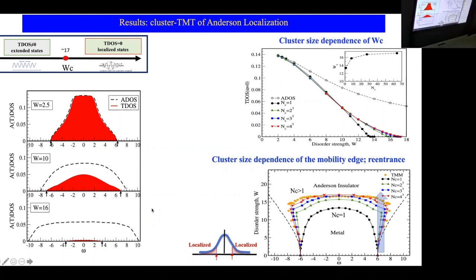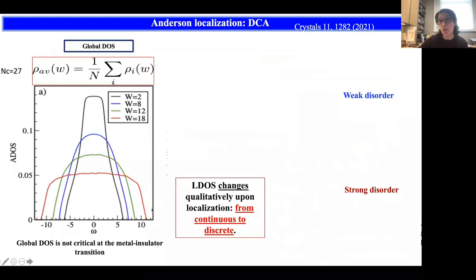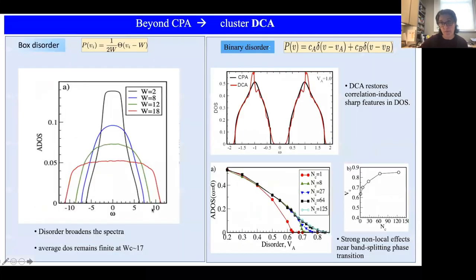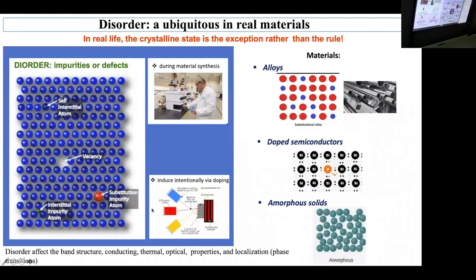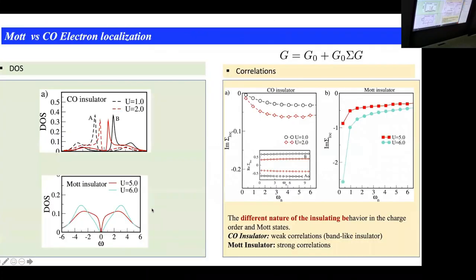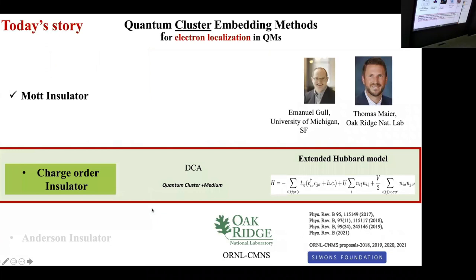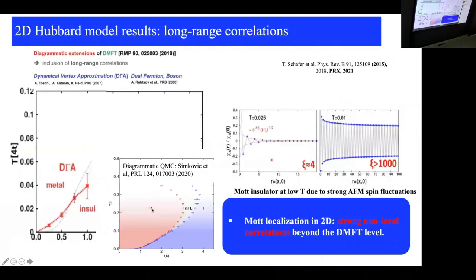But in the D gamma A, you showed... In D gamma A, it's a different story. This D gamma A is just to show where the origin is coming from. It's clear that even if you enforce paramagnetism, if the system is big enough, it will have local antiferromagnetic correlations. They will dominate the structure factor. It will just rotate basically so that the average is zero, but the correlations will be there. So what's interesting is to look at the frustrated lattice then.